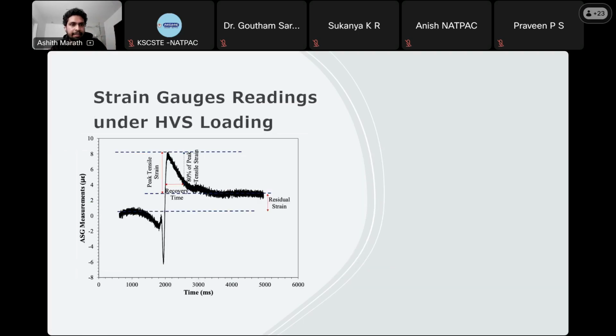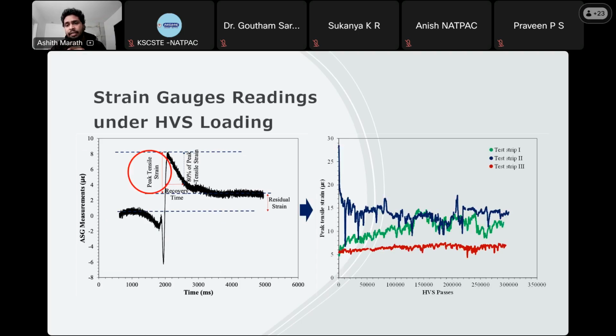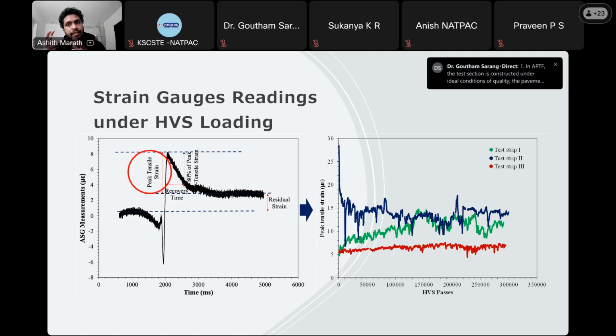And finally, the strain gauge readings. As I mentioned, we installed longitudinal strain gauges. So we tried to use the peak tensile strain values and plot them against the number of HVS passes. The idea was to look at the susceptibility to fatigue cracking of the pavements,